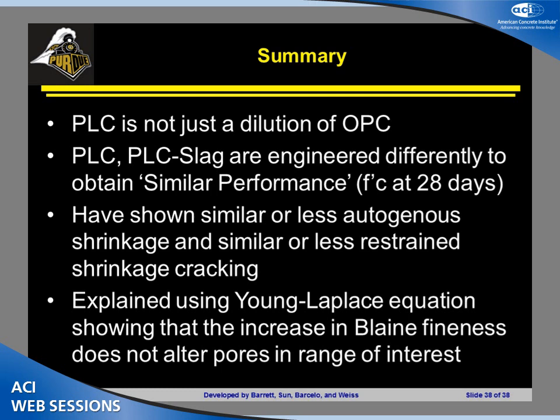We've shown similar or less autogenous shrinkage with the PLC and the PLC slag systems, and this means that we have similar or less shrinkage cracking. And I believe all of these observations, in addition to being experiments that have been performed, can really be explained by what we've seen with the Young-Laplace equation and the very similar pore size distribution. So with that, I'll turn it back over to our speakers. Are there any questions, Mason?